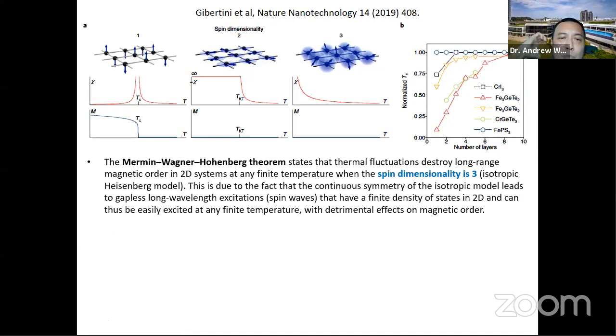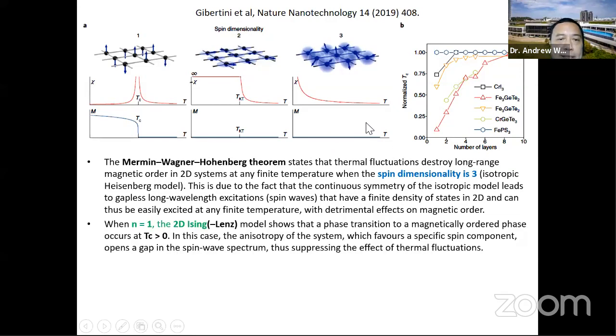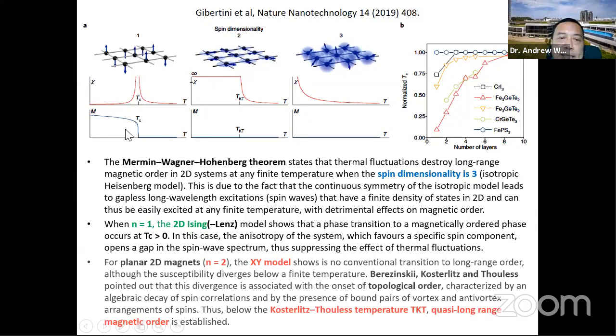So to summarize, the Mermin-Wagner-Hohenberg theorem says that thermal fluctuations destroy long-range order in 2D systems at any finite temperature when the spin dimensionality is 3. That means in this isotropic system, it's an isotropic Heisenberg system. You can see there's no magnetism here, right? On the other hand, the 2D Ising system, you can get a phase transition at Tc, and Tc is greater than 0, it's magnetic. And in the planar 2D magnet system, in this case, spin dimensionality of 2, the XY model shows that there's no conventional transition to long-range order, although you get susceptibility diverging below a finite temperature.